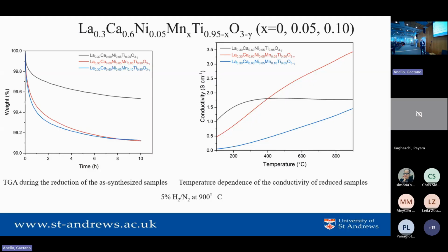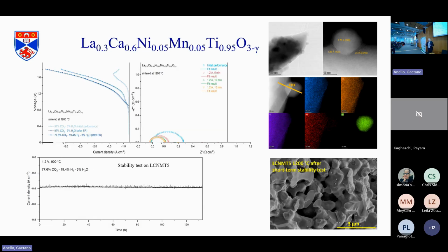If you put manganese into the titanate, you see that when you reduce it, it reduces much quicker. Manganese promotes oxygen transport. Without manganese, it's quite slow. The conductivity change as you reduce is much more marked with the nickel and manganese, even though the manganese doesn't help the initial conductivity in reducing conditions. So manganese makes nickel easier to reduce, and then you get very nice nanoparticles. So the nanoparticles are nickel, not nickel manganese, and they're sitting on the surface.